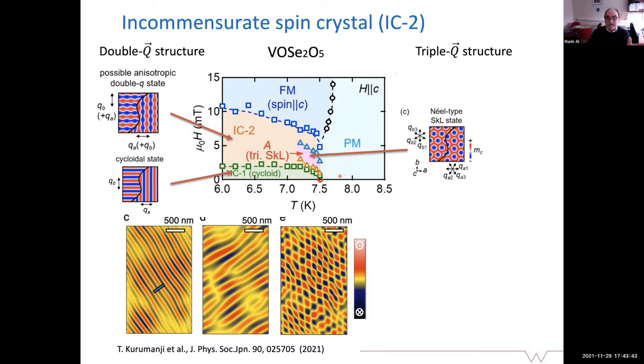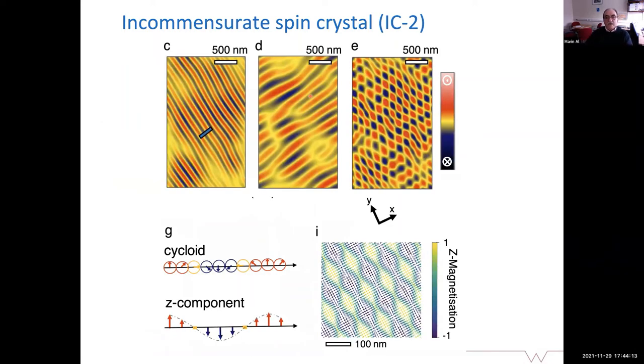And then the idea was that it's pretty easy to compare them and to say, look, this is exactly the phase we are seeing there. So it's the double Q periodicity, which we see now in real space, not in reciprocal space, as it has been determined in this very particular crystal by neutron diffraction. So, in other words, we have that phase, which we believe is a cycloidal phase, because we have detected exactly this type of sinusoidal transition between those phases which are running perpendicular to the main periodicity.